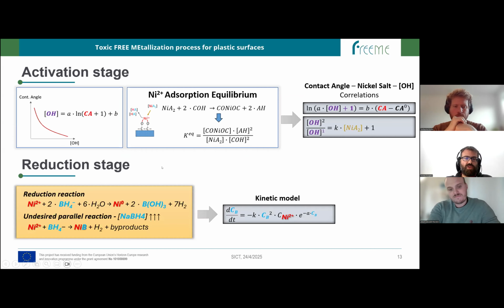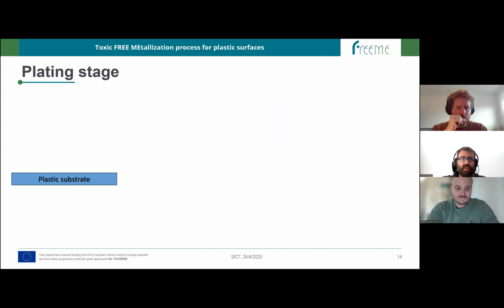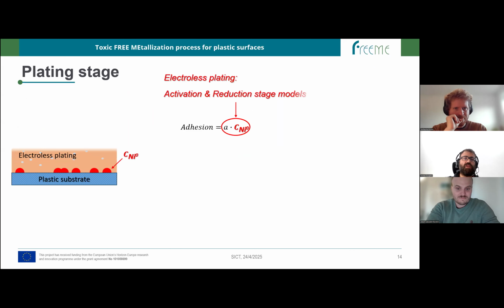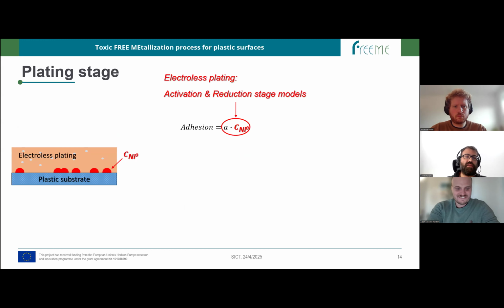While for the case of the reduction stage, we have also developed a kinetic model, and by combining all these models, we could estimate the concentration of the nucleation sites on the surface. And by knowing this, you can go to the plating stage, and make a correlation to estimate and predict the adhesion for different conditions. Here you can see in red dots the concentration of the nucleation sites made by the previous stages, and we have also identified that there is a correlation of this concentration, based on which the electroless plating is spread across the whole surface and making this layer.